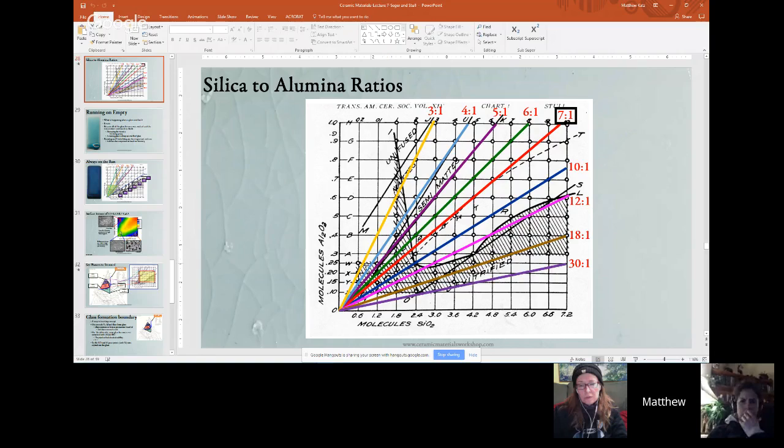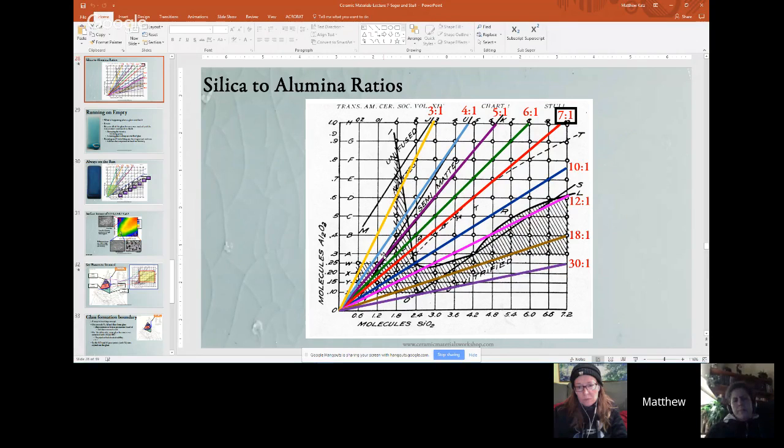But again, really what it does is overload the system with different silica and alumina. You're also really bringing up the R2O levels, because you have to remember, in this lower corner, from a UMF perspective, there is 1 mole of flux, but when you're under the 0.3 alumina level, there's so much flux compared to the glass formers that the fluxes sort of take over.